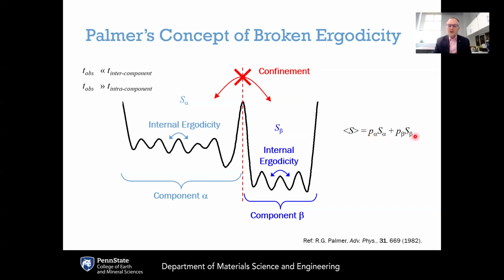Likewise, there would be an entropy of the system if it is confined in component beta. That would be based on the number of microstates in component beta, and that's given by S beta. And then a corresponding probability of being in component beta, which is P beta. And therefore, if you do this weighted average, where you take the property values within each component, S alpha and S beta, multiply them by their corresponding probabilities, P alpha and P beta, and add them up, that would then give you the expectation value of the property, so the expectation value of the entropy in this case.